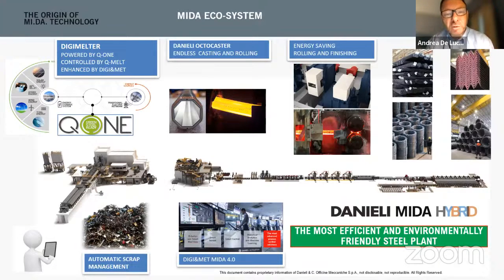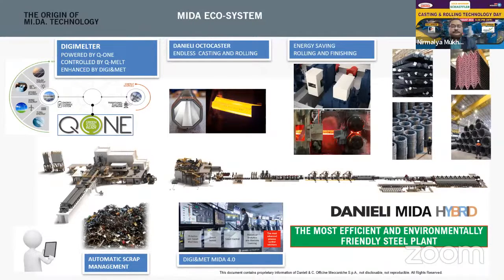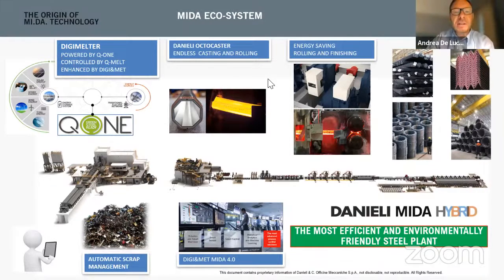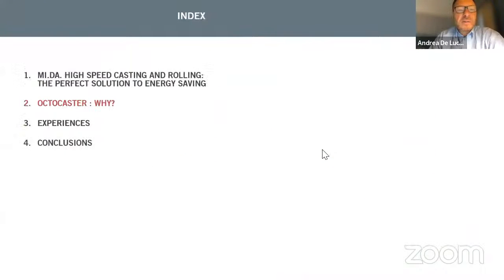But the very core of the Endless Cast technology is the caster, which needs to perform at very, very high casting speed. We need at least 4.5 meters per minute to connect the caster with the rolling mill in Endless, but industrially, the efficiency starts when we exceed 6-7 meters per minute. And the Octocaster, as I will explain, is the technology that is working worldwide now for this purpose. Then finally, energy-saving rolling and finishing. We are cutting to length directly on the rolling mill, so no cold cutting and no worse yield in the last part of the plant.